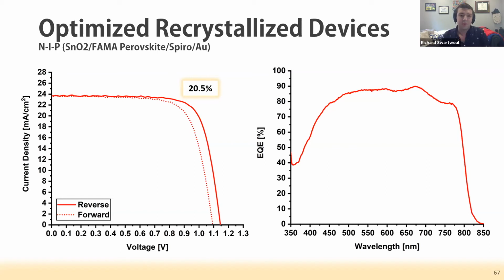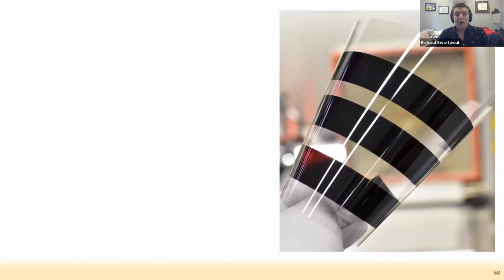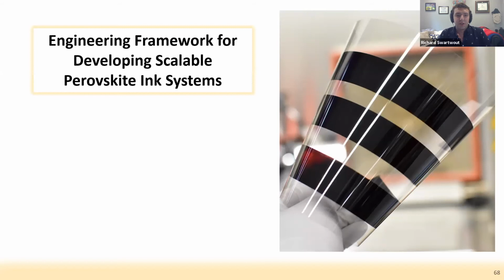With that, I am going to conclude the technical portion of my talk and leave the rest up for questions if desired. Today I've presented two things: the first being an engineering framework for developing scalable perovskite ink systems. The rule of thumb takeaway is don't use anything lower than 100 parts per million permissible exposure limit, and ideally, from an EPA perspective, choose solvents that are not regulated as hazardous air pollutants.